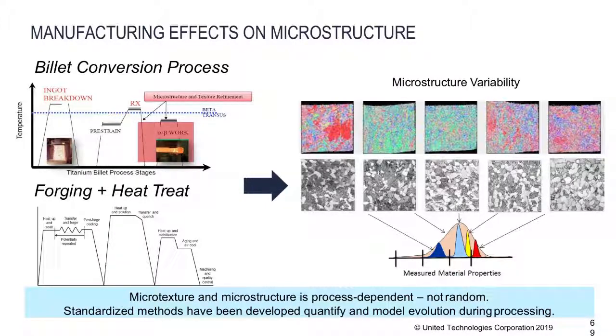It seems to be set, but it can certainly affect your microstructure, as you see on the bottom. On the bottom to the right, you have different volume fractions, different sizes of primary alpha based on the cooling rates. And up top, you have different levels of microtexture, particularly really bad on the left, and some others are in that gray area of, you know, how good is it. But I think we all say that the left one is probably the worst from an inhomogeneity standpoint.